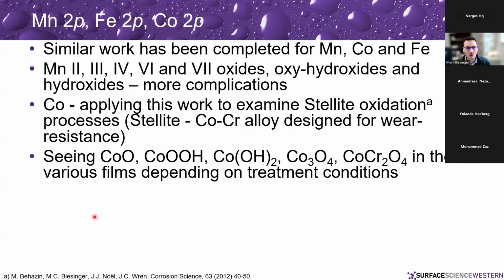So we've done similar work for things like all the first row transition metals, manganese, iron, cobalt. With something like manganese, you've got manganese 2, manganese 3, manganese 4, manganese 6, and manganese 7 oxides, oxyhydroxides, plus other carbonates and sulfates and all that sort of stuff. And all of them are going to have unique peak shapes, overlapping binding energies, some shake-up structures and things like that that you'll have to take into the model to pull out what you have.